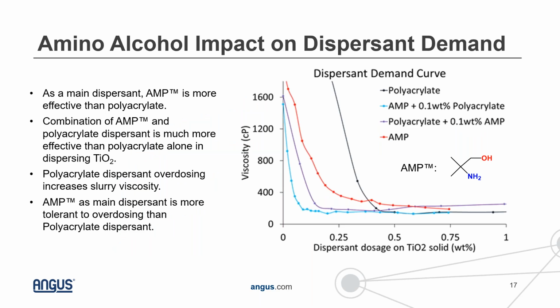And you can measure or quantify this effect in a coating formulation by looking at a dispersant demand curve. These dispersant demand curves are generated by taking a grind of pigments or just TiO2 and slowly adding or introducing your dispersing agent. Plotted on the x-axis is the dispersant dosage on TiO2 as a weight percent on solids, and plotted on the y-axis is viscosity. As you break down those particles from their agglomerates into their primary particles, there's a correlation not just with the particle size, but also with the viscosity. So a decrease in viscosity correlates to a smaller particle size in your slurry or your grind.